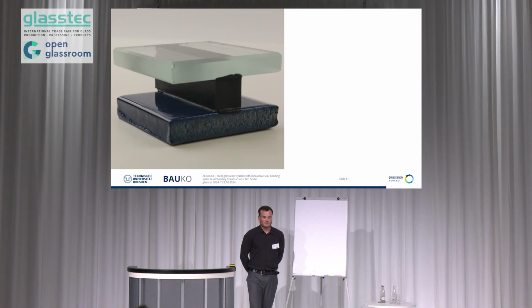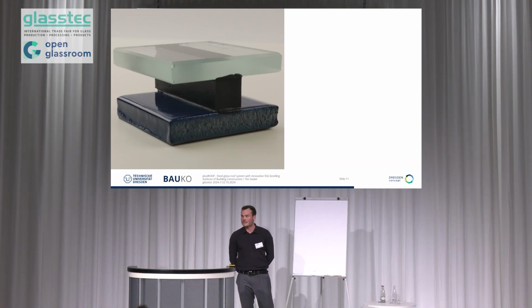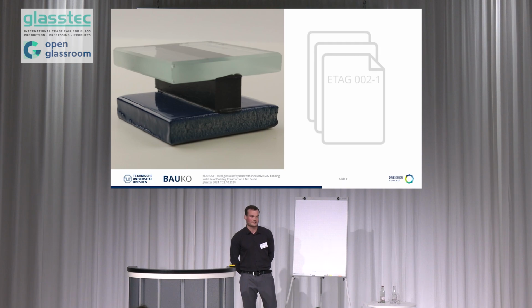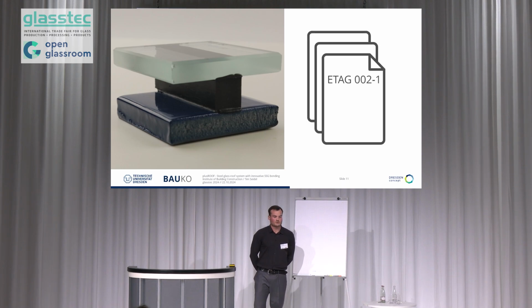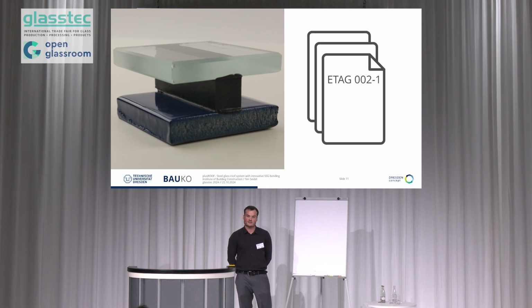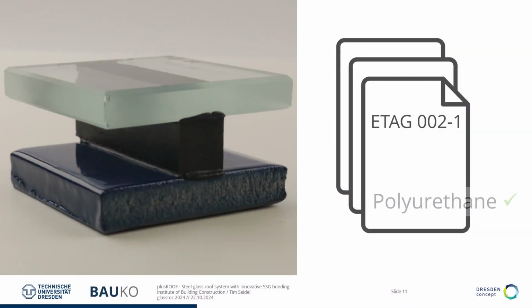For the choice of the best coating, adhesion tests on H-shaped test specimens were decisive. The ETAG 002 Part 1, a guideline for bonded glass constructions, regulates such tests. The best results were achieved by the polyurethane coating that met all the requirements of the ETAG.